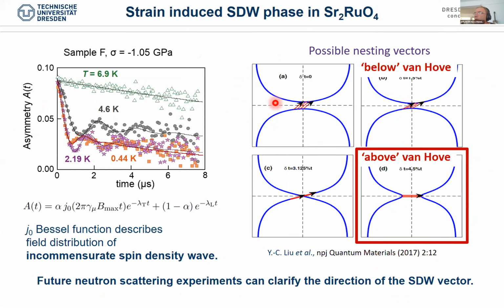Yeah, the physics of that has already been proposed in different ways. If we approach the Van Hove singularity, in this theoretical study, there are different ways to form a spin density wave order by nesting on the Fermi surface in the vicinity of the Van Hove singularity point. In the theory, it was actually predicted that you should already have spin density wave order below the Van Hove singularity point. That would be figures A and B in this study. However, we clearly only see the magnetic order above the Van Hove point.